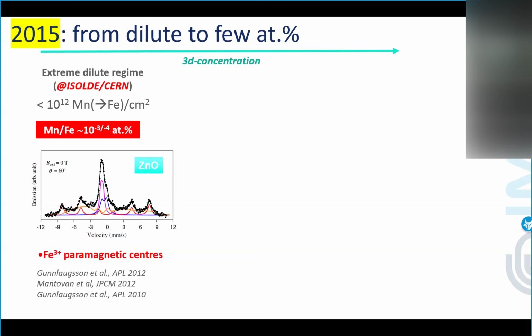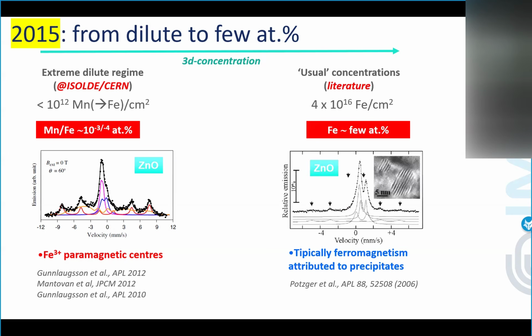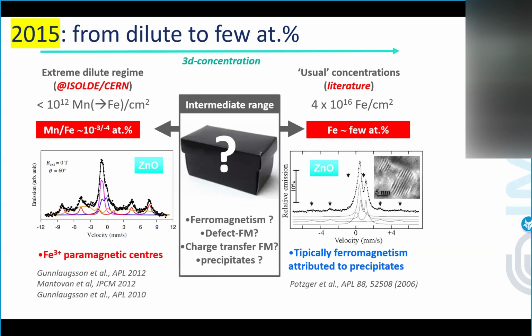We know that at the ultra-dilute regime, we are dealing with a slow relaxing paramagnetic center. At the literature concentrations, which were typically used by people doing Mössbauer spectroscopy, the group of Potzger did a lot in this direction. They observed that finally they have precipitates when they see ferromagnetism. But what happened in between was a sort of mystery for all of us. So there could still be any possibility of having long-range ferromagnetism at some point, but we didn't know whether it could happen at some precise concentration.